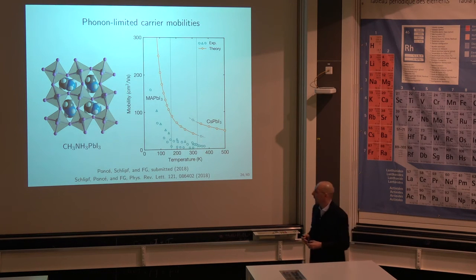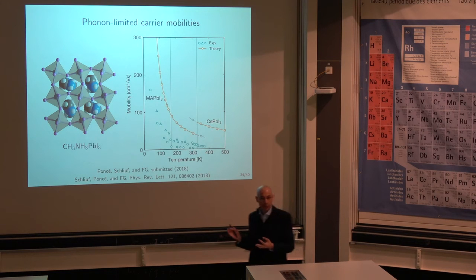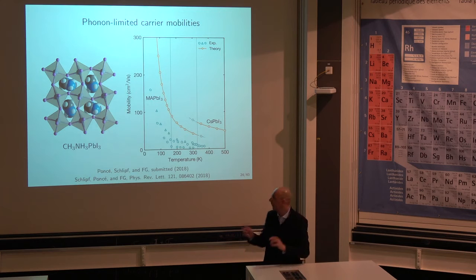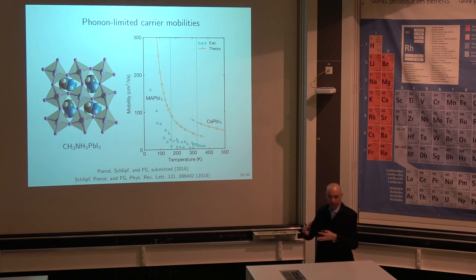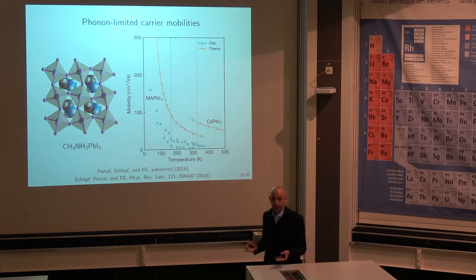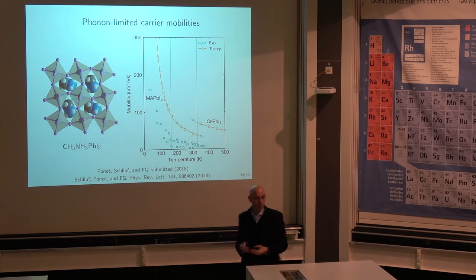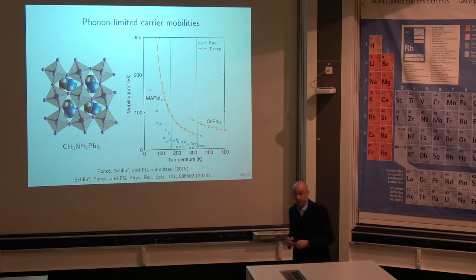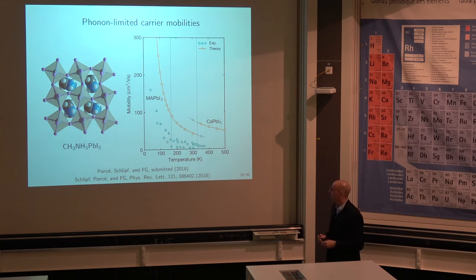this compound. The challenge is that if you look at the low temperature structure, which is the one where the molecules are not really moving around, so you can talk about a crystal, the structure contains 48 atoms. So we're talking about mobility calculations on 48 atoms, and that's actually very challenging. This forced us to burn a lot of computer time, but in the end we got our data.